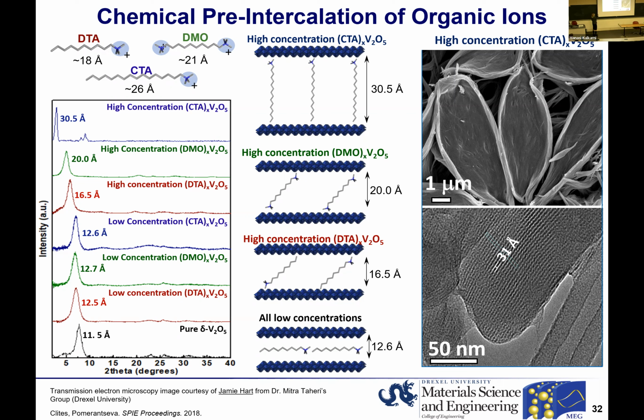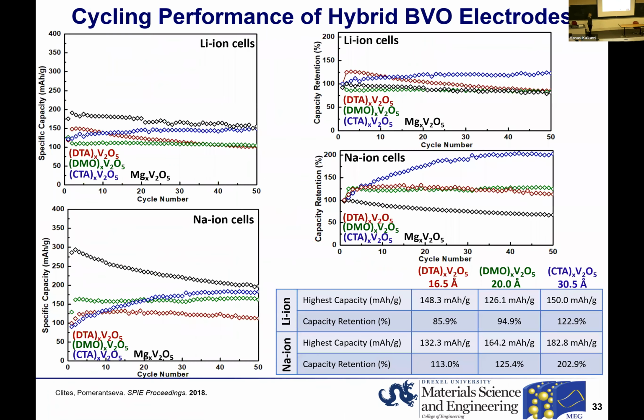And we got the material with the interlayer distance of 30 angstrom, which we didn't believe for a very long time until students from Professor Taheri's group took some TEM images for us and confirmed that indeed we have a material with such huge interlayer spacing.